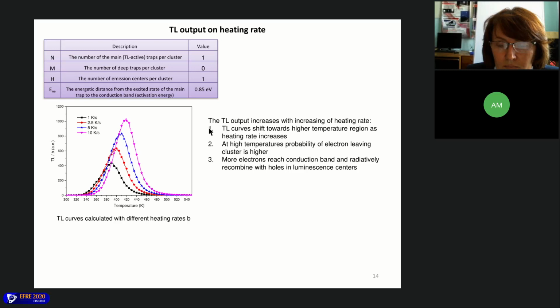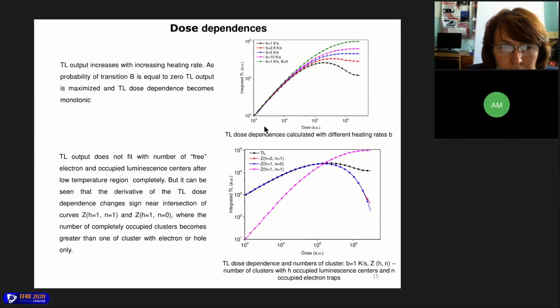Since at high temperature the probability of an electron leaving the cluster is higher, more electrons reach the conduction band and radiatively recombine with holes in luminescence centers. This effect is called in the literature the anomalous heating rate effect. The effect is also noticeable in the figure with TL dose dependencies. Also, in this case, at low heating rate, the TL dose dependency is non-monotonic. It can be explained by approaching the extreme case when all delocalized transitions are executed before the localized ones.